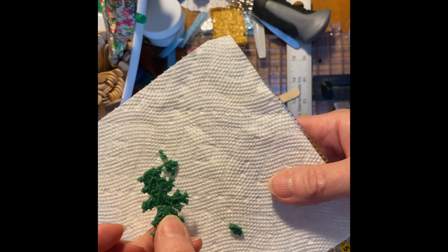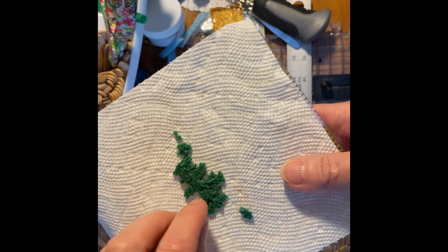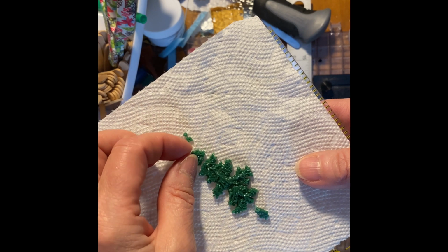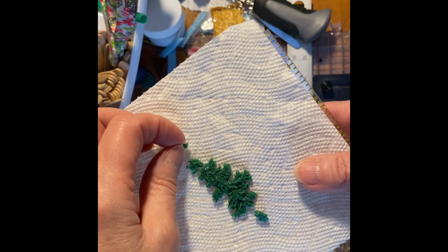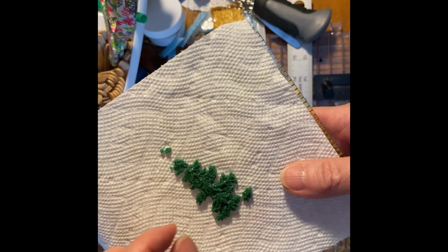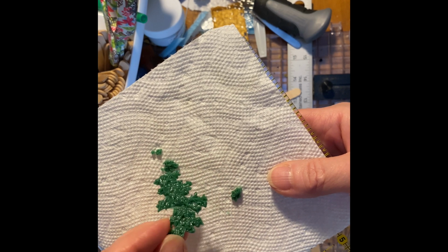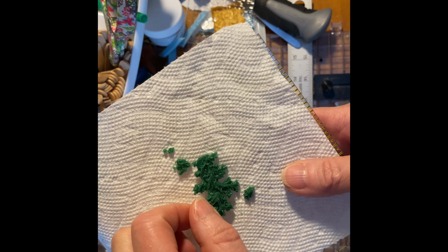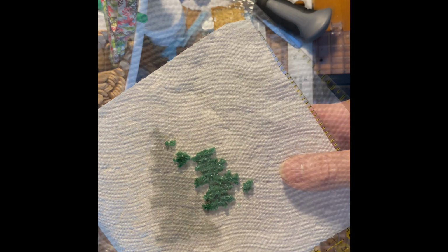You'll see where it's very thin. I don't know if you can see the light through it. There's a very thin spot right there that you can see light through. And then the top, the thin spot was so thin that it couldn't hold its shape. This was caused by simply not having enough glass powder in the slurry. Once all the water evaporated, there was really nothing in that space.